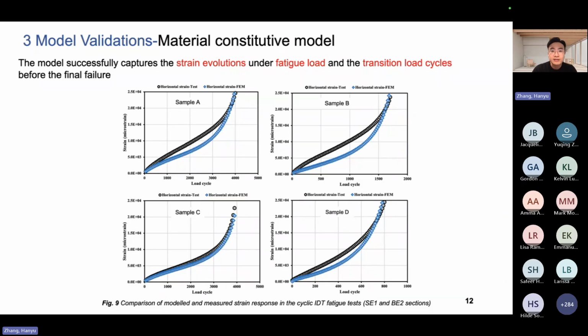In this slide, I'm going to show the validations in terms of the material constitutive model, that is the viscoelastic continuum damage model. This figure shows the comparison of the modeled and measured strain response in cyclic indirect tensile fatigue tests for the field cores. What we see here, the model can capture the strain evolutions under the fatigue load and the transition load cycles before the final failures. So the model is valid in terms of describing the asphalt fatigue damage behaviors.